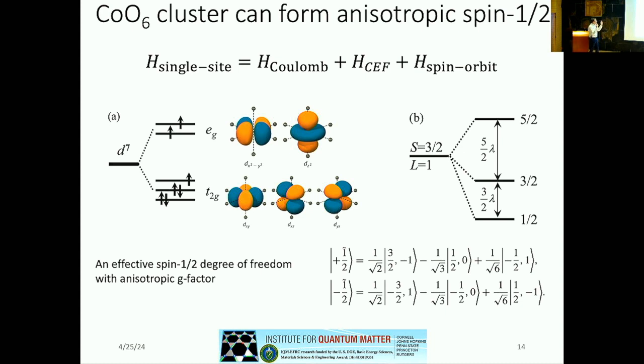So let me say a few words about how this all proceeds. I'm thinking about just a CoO6 cluster. So I have the oxygen, and then I have my cobalt sitting at the center. And what are the relevant interactions? Well, they are the Coulomb repulsion between electrons, which are all negatively charged. There's also a repulsion between the electron and the neighboring ligands, which is the oxygen. That's what we call the crystalline electric field effect. And then there's a spin-orbit interaction between the spin and orbital angular momentum of those d electrons.